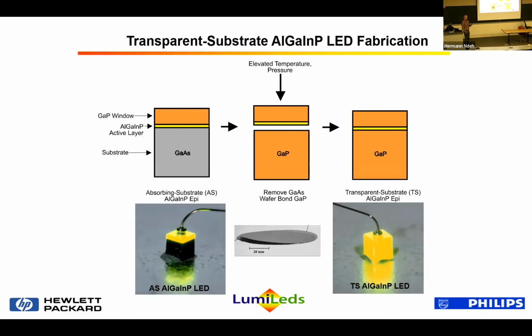So we use this technology then to make high performance LEDs. We started with an aluminum gallium indium phosphide layer that was lattice matched to gallium arsenide, grew a metamorphic gallium phosphide window by VPE, etched the gallium arsenide substrate off, and wafer bonded the two materials together. And then again, you see this is literally a 3-inch wafer of an LED and a gallium phosphide substrate. And with that, we produce transparent substrate devices.